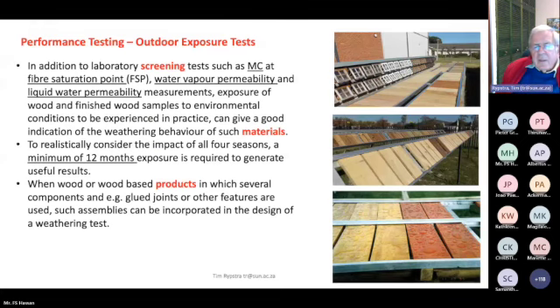So performance testing, that's another thing that can be done in addition to laboratory testing, as you saw on the previous slide. Water vapor permeability and liquid water permeability are measurements that can help to find out whether the amount of weathering can be reduced and the effect of that. So that's a typical study which is done on materials, and you can see here that exposure, natural exposure of wooden pieces without any structure, as you will see on the right at the top here, there are window panes which are different to weather than if you are looking at 45-degree or horizontally samples which don't have any processing other than planing and the application of certain coatings or doing certain changes to the structure.